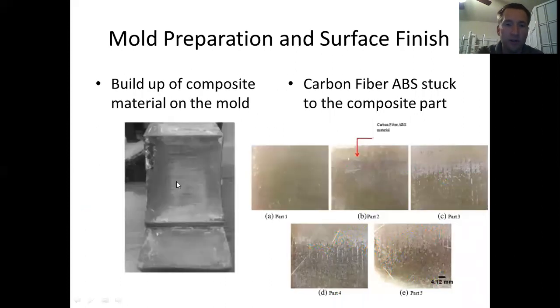So here's some pictures of the buildup on the mold. So this is composite material. This white area is the composite material building up on the mold. And then these pictures on the right are the carbon fibers from the ABS, the carbon fiber ABS mold that was sticking to the composite part. So the more times they used it, the more likely they were to get that carbon fiber ABS stuck to the composite part.